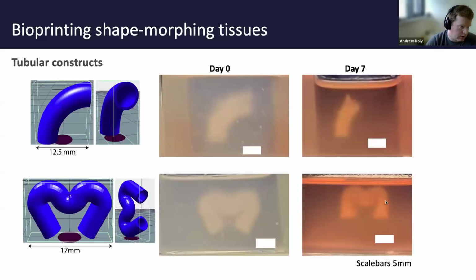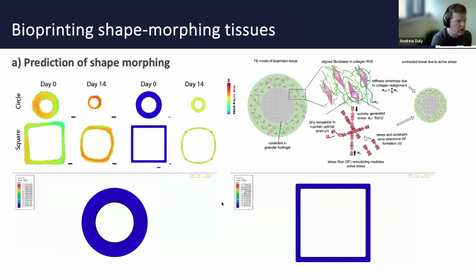And we could scale it up. So if we print this tube structure or tubular M structure, the stresses within the tissue during culture would cause it to change shape. So we saw straightening of this bent tube and gradual opening of these M structures. And this is just looking at an angle of them morphing within the support bath. I won't go into too much detail on this.